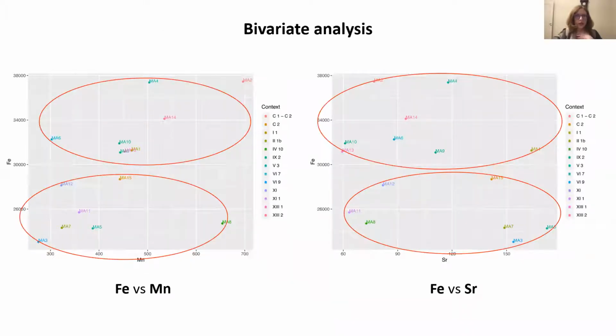Now we go back to the samples and specifically the topic of this presentation, what's happening with the mudbrick in the Malian Palace. Our next step was to perform a bivariate analysis by isolating the values of iron, manganese, and strontium. The samples are discriminated here on the basis of the location of the sample within the palace. To briefly explain, strontium, as I mentioned before, is associated with carbonated rocks, while iron and manganese refer to the non-carbonate content, such as ferromanganese silicates or illitic mud.